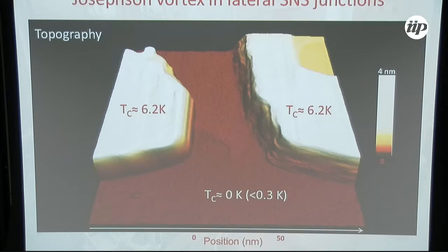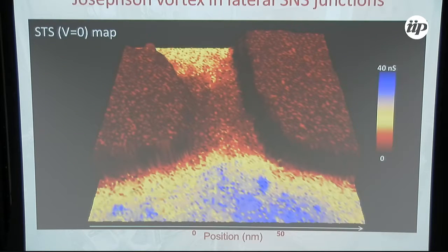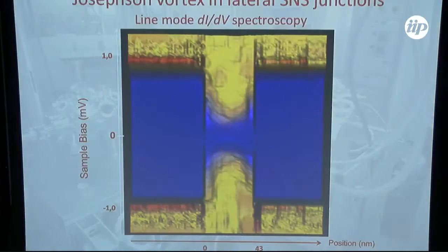Now, of course, if you put two islands close to each other, you see experimentally, by tunneling spectroscopy, that the color gives the strength of the superconducting correlation. You clearly see a depletion due to these Andreev quasiparticles. This is a top view of the spectroscopy. In blue is the superconducting gap of lead on each island, left and right, and here you see the depletion in the tunneling characteristic due to Andreev quasiparticles. So we use this depletion in the spectrum to probe Josephson vortices inside.